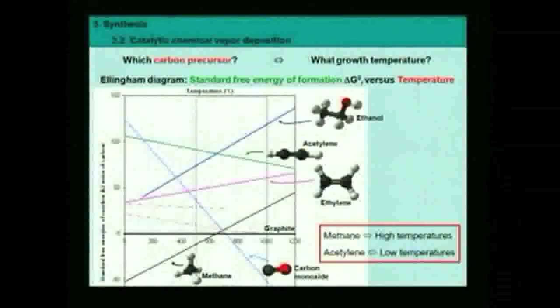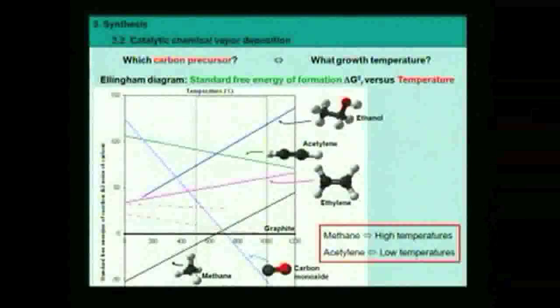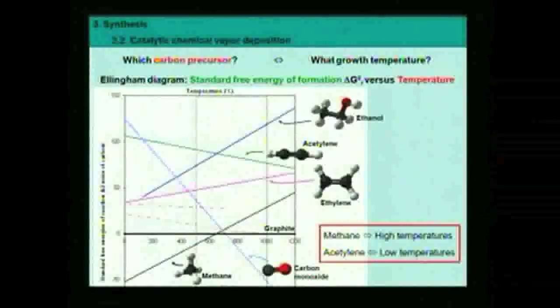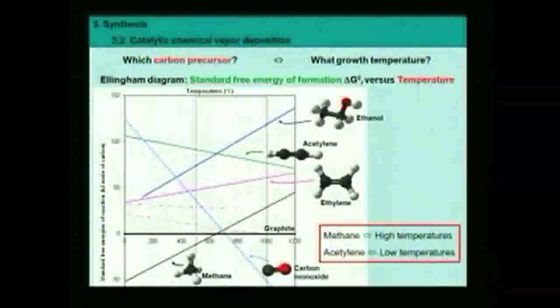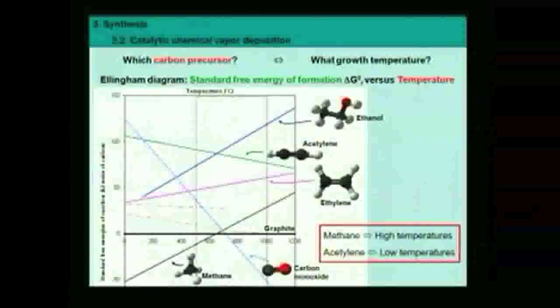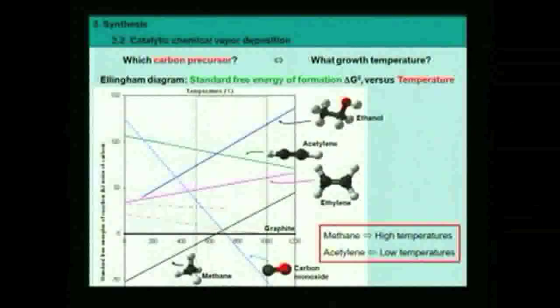And another precursor you can use is ethanol. What is interesting here is that together with carbon and hydrogen you also bring oxygen, and this oxygen can be useful or not during the synthesis. You also have to take into account that you bring something else. It's not only carbon you bring in. With this carbon precursor you also bring hydrogen and oxygen, and these are important elements that can react together with carbon.